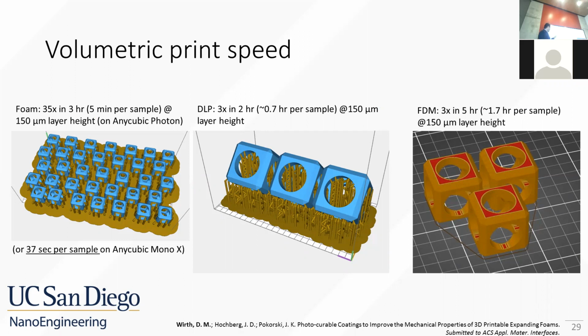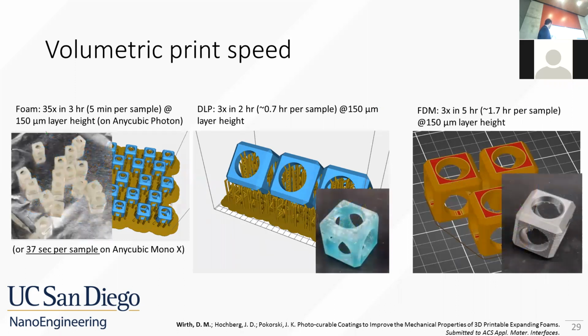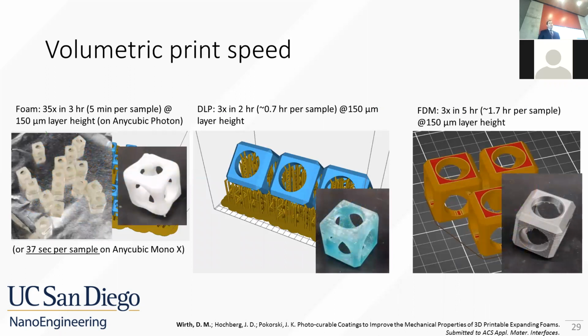If we use an isotropic expanding foam process, we can get the effective print time for a 1-inch sample cube down to 37 seconds per sample. This is because the samples are much smaller, so we can print them much faster, and using a highly parallelized process, we can fit many more of them onto the build plate.